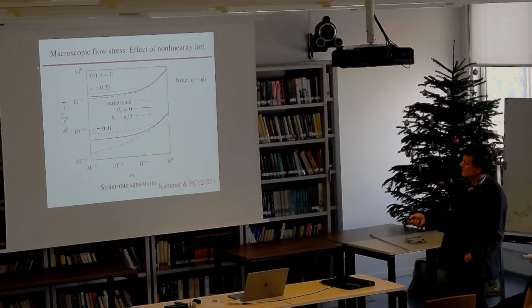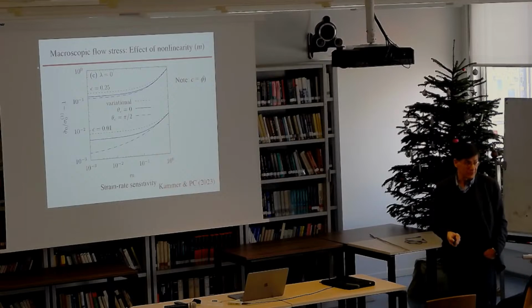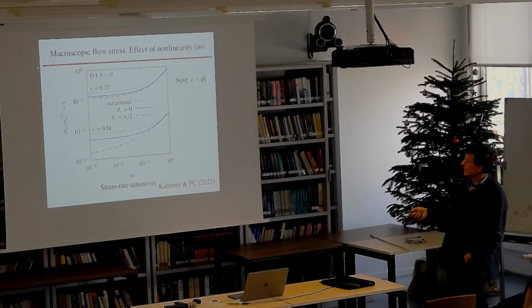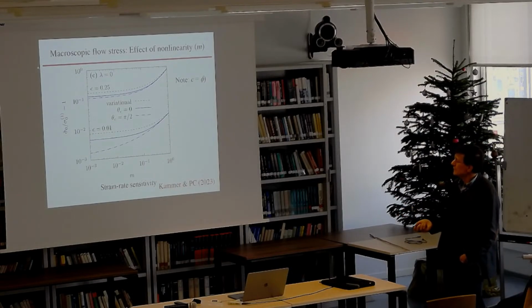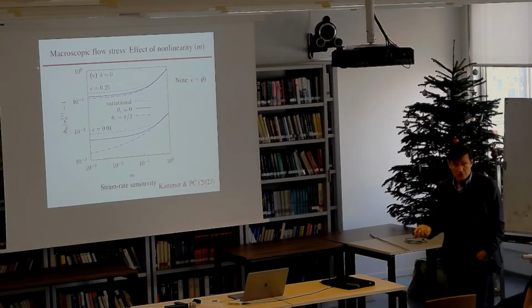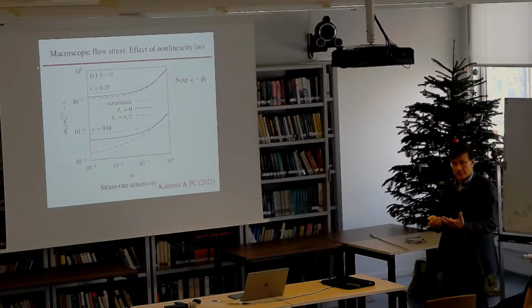But for shear, you get a softer response than for axisymmetric. This is the variational estimate, which is an upper bound, but doesn't depend on the type of loading. So the results that we get are consistent with this difference.